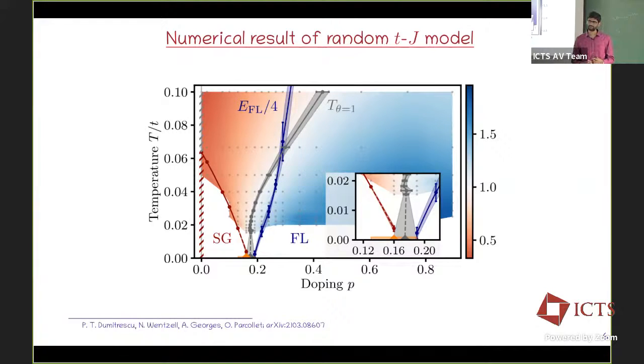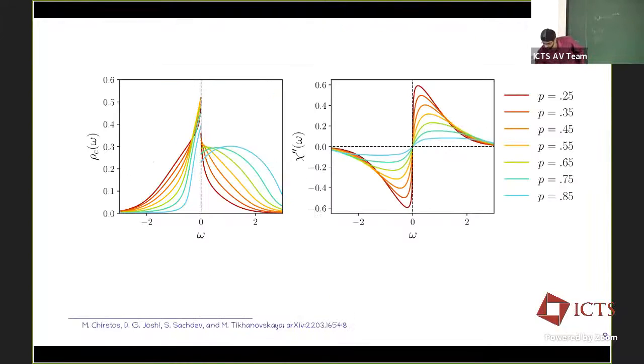So you're saying that your prediction and these models are telling you that if you do ESR in this highly doped region, you'll see some anomalous behavior. What would you see? The local spin correlation won't be linear in omega, but it would have some different power law, like what I was showing. So especially near the strange metallic region, you should not see a linear behavior, but some very strange power laws. That would be an interesting observation to test this.